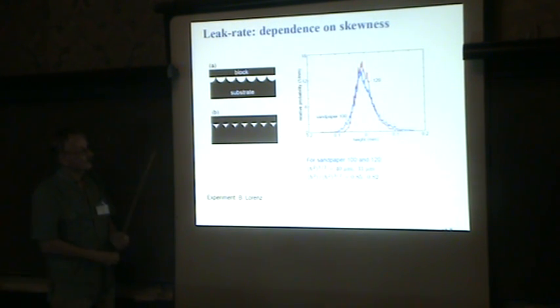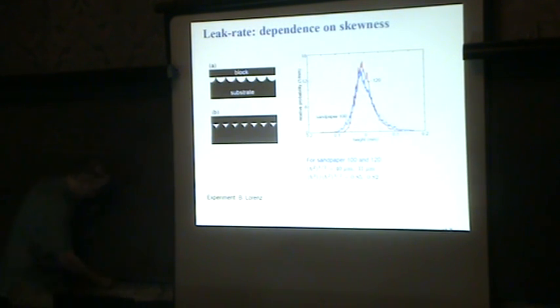So what we have done is use in our calculation not the power spectra of this surface or that surface, which are the same, but what we call the top power spectra, when we calculate leakage. And for the top power spectra, basically, you take your measured surface profile, I will take something which looks similar, put in the average plane, and then basically we assume that things below the average plane look the same as above, and not like they actually look, but more like they looked above.